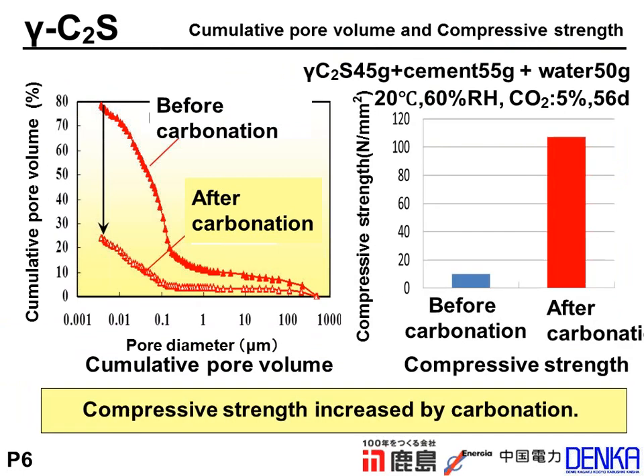The right figure is the compressive strength of the same paste specimen. The value before carbonation is around 10 Newton per square millimeter. On the other hand, after carbonation, the value is over 100 Newton per square millimeter. The compressive strength increased by carbonation.